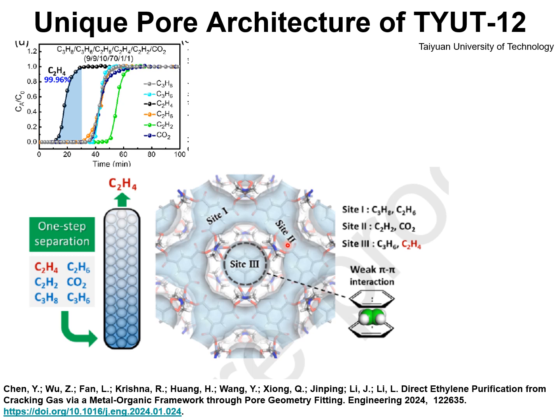Site 2 absorbs preferentially C2H2 and CO2, whereas site 3 with very weak pi-pi stacking and pi interactions allow absorption of propene and ethene. And of these 6 components, the component with the lowest absorption strength is ethylene.